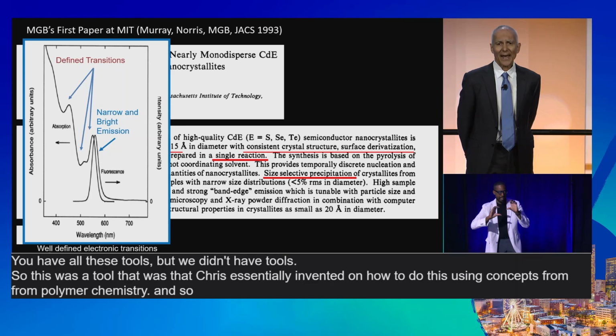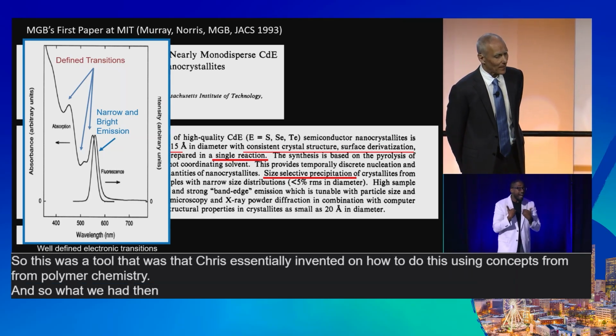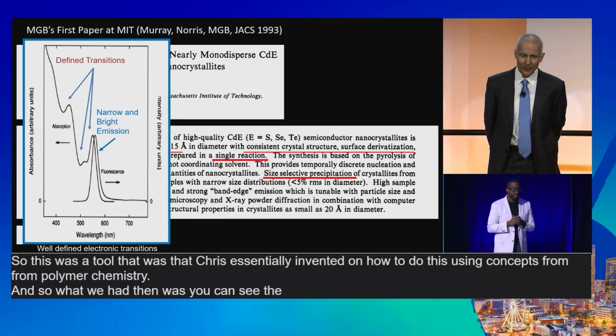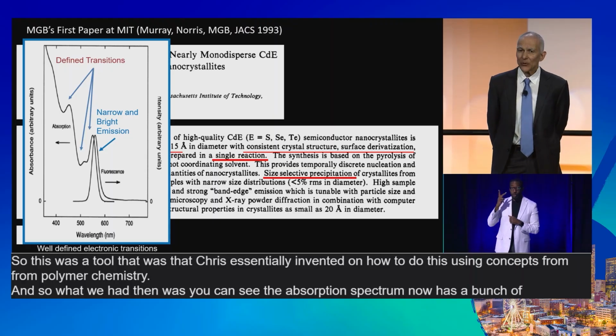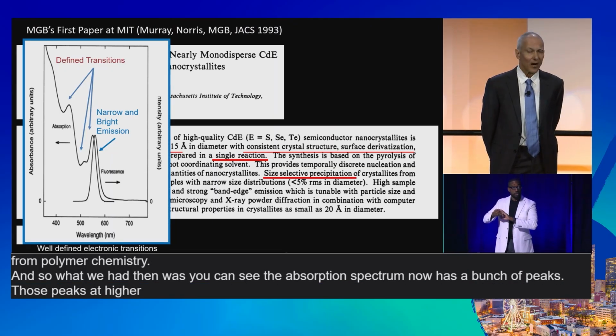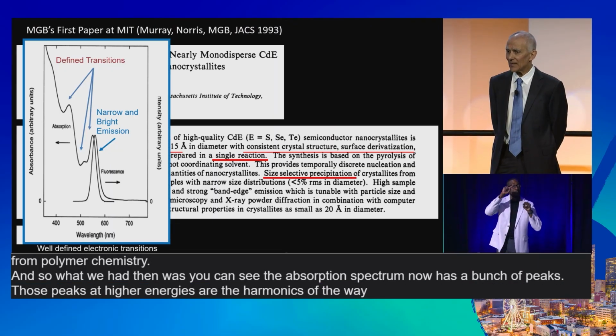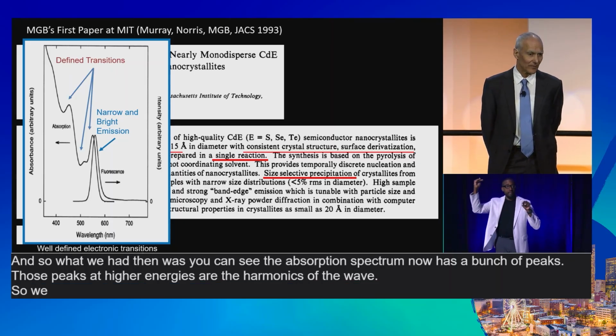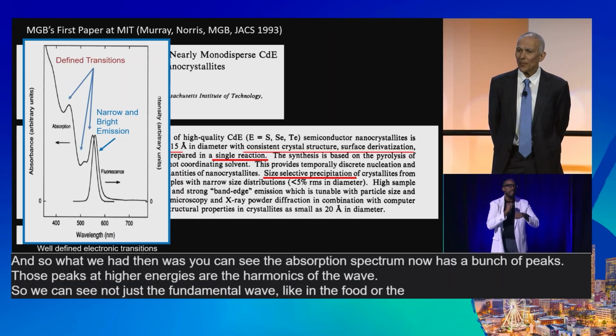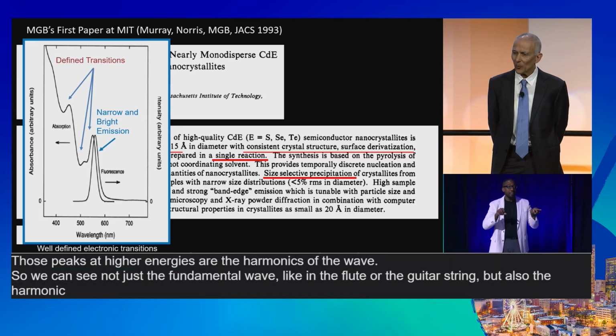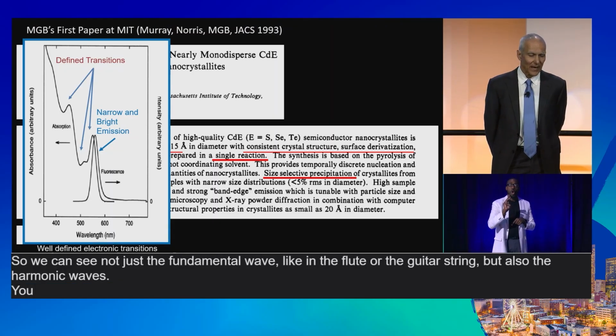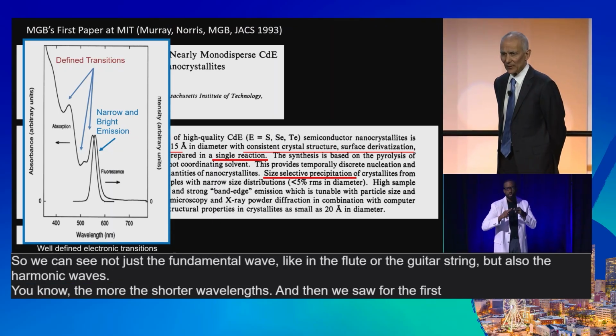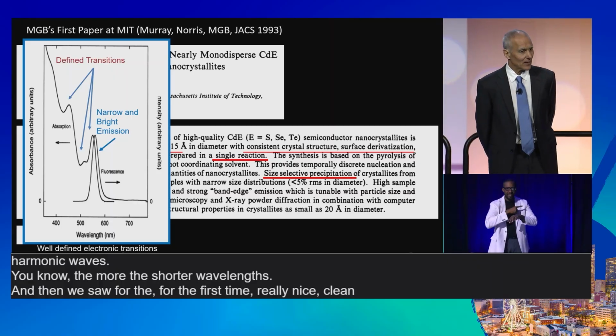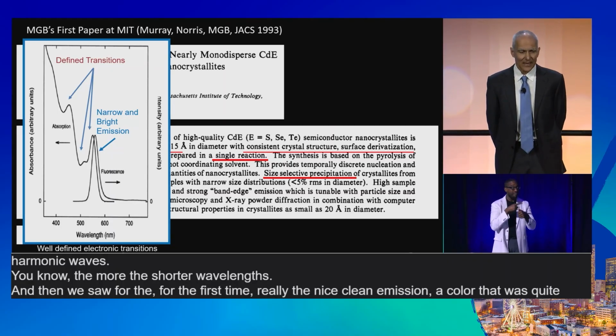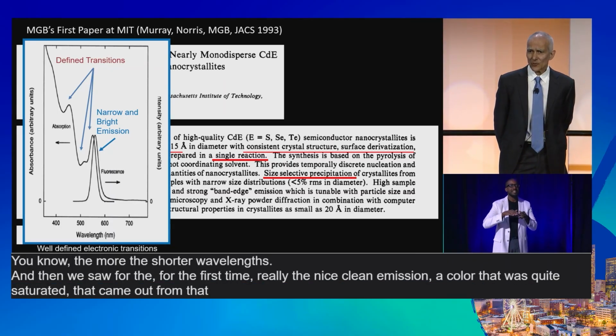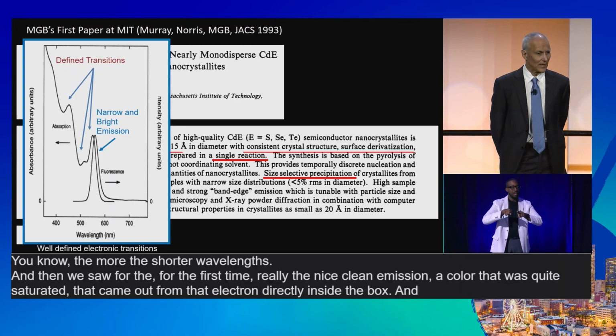And so what we had then was, you can see the absorption spectrum now has a bunch of peaks. Those peaks at higher energies are the harmonics of the wave. So we can see not just the fundamental wave, like in the flute or the guitar string, but also the harmonic waves, the shorter wavelengths. And then we saw for the first time, really, a nice clean emission, a color that was quite saturated, that came out from that electron directly inside the box and not from some defects.